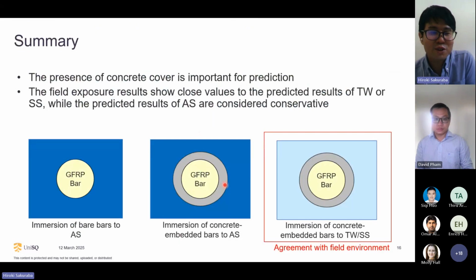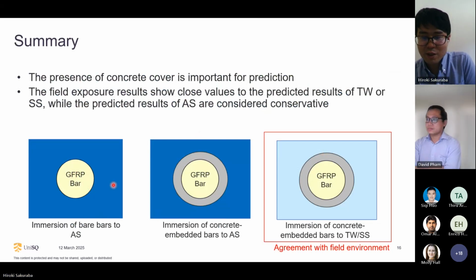So in conclusion for this topic, the presence of concrete cover is really important for long-term prediction. And also the field exposure results show close values to the predicted results of tap water or saline solution, while the predicted results of alkaline solution are really conservative. Normally we conduct immersion tests using bare bars in alkaline solution, but this can give a really conservative result. From my study, immersion of concrete embedded bars in tap water had a good agreement with the field environment.